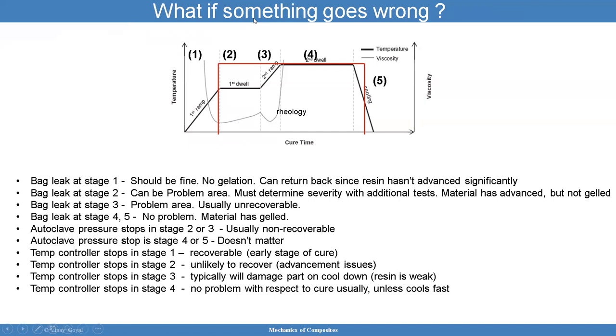You have a bag leak now at stage two. That can be a problem area because I start to have some amount of gelling. It's not fully gelled, but you may want to determine the severity of what occurred there through additional testing. That's what's recommended. Now, if you have a bag leak here in the second ramp, now we're looking at a problem area because now you're into the gelation and the bag leak is supposed to be there for consolidation to make sure the voids are getting removed. Right, and if I'm not getting that, that could be a problem.